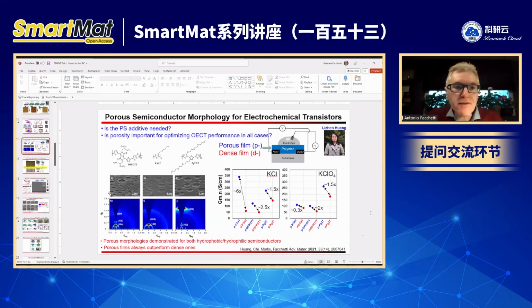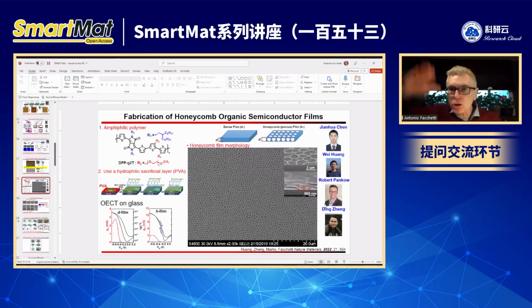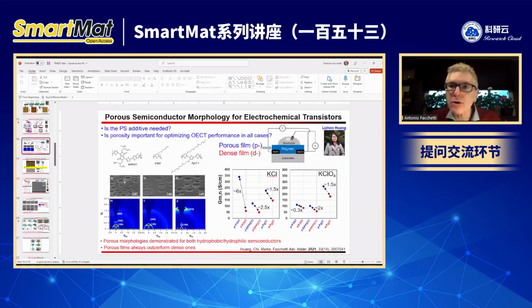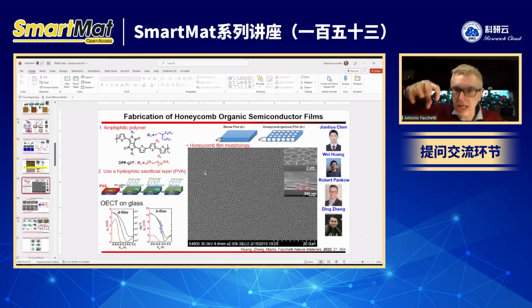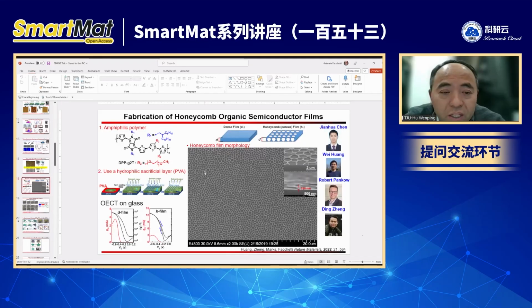Instead, this film was fabricated on glass or silicon oxide with a little bit of polyvinyl alcohol film on top. And then you deposit your polymer. And the PVA likes water very, very much, in a very controllable manner. So the water can condense here very well. And this really creates this self-assembled morphology that gives this porosity. So really you need this PVA. It makes a huge difference in going from this morphology, which is more crater, to this morphology, which are really holes that go through. And also, it actually shows strong substrate dependence.